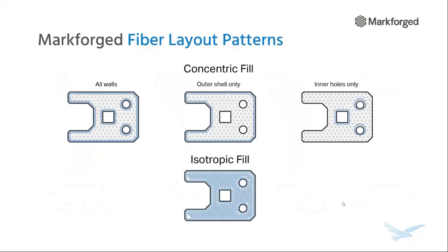But then we have there at the bottom isotropic fill. And notice how those fiber strands are laid out in a specific angle, about 45 degrees. And so with isotropic fill, you're able to really dial in the direction of those fibers in order to maximize the performance of that part under a given loading condition. And you could even choose to alternate the angle of those fiber panels as you move up in the z-axis as you're printing. And what that does is provides multi-directional part strength.